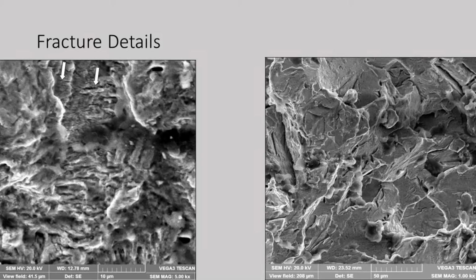And just as a little note here, I wanted to show you this. If you ever went to a materials class that talked about steel and fatigue, they always mentioned fatigue striations, okay? To see those, you really have to kick the magnification up at least 2,000 times. And this picture here is at 5,000 magnification of that thumbnail area. Just to verify that's a fatigue crack, you can see these little steps here, here, here, here. Those are fatigue crack striations. That's where a crack stops and grows in one load cycle.